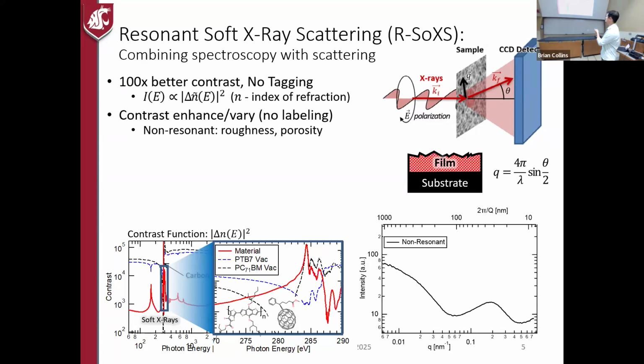So for example, non-resonant would be more sensitive to roughness or porosity. And so here's an example of a scattering pattern from that. This is intensity as a function of scattering angle or Q, shown here. That's the momentum transfer of the photon, and that's just like the scattering angle, really. I've also plotted here 2 pi over Q, which is kind of your Bragg equation, to look at what size scale we're looking at at different angles.